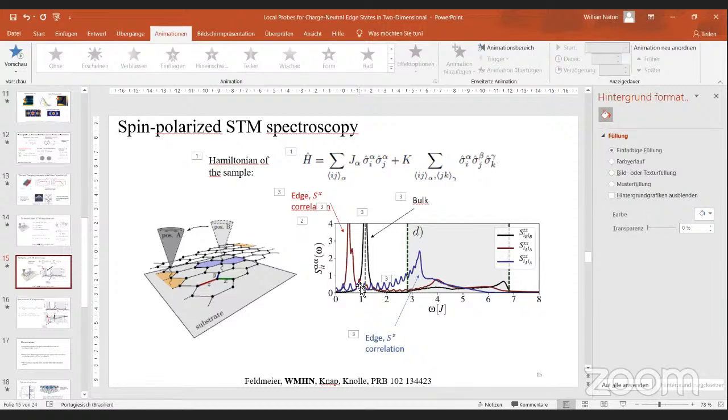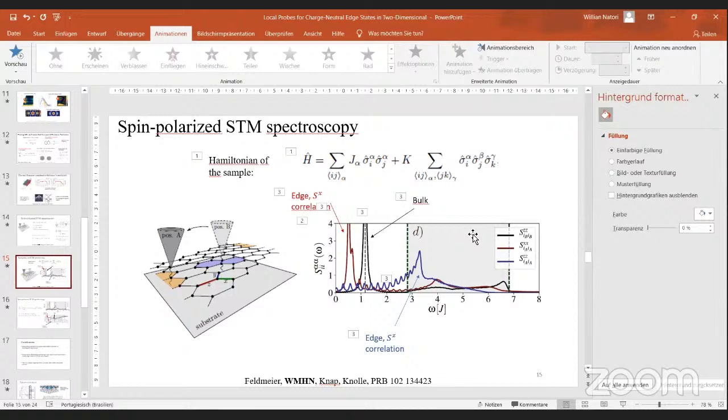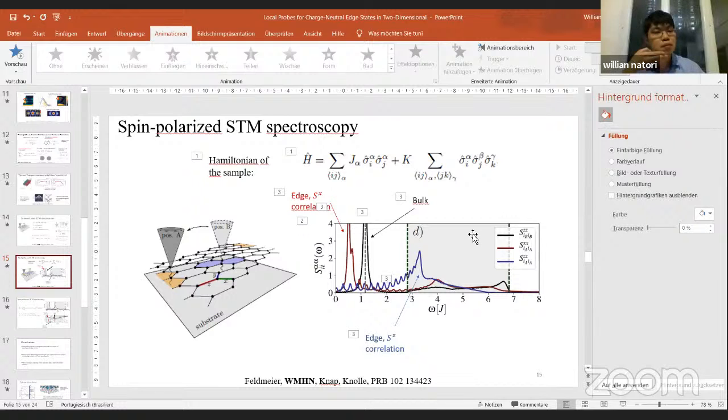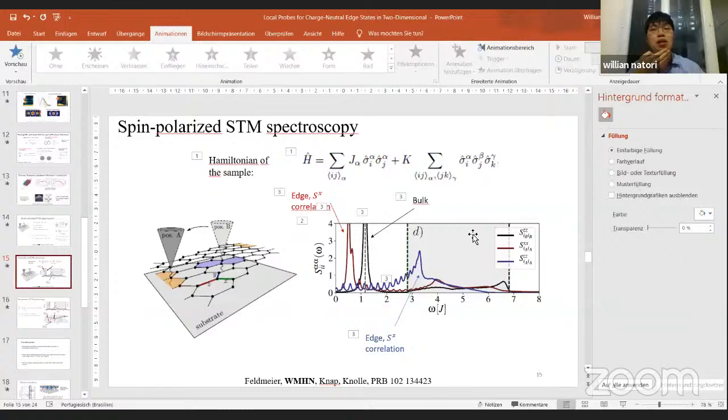For 213, it has this honeycomb structure and the zigzag antiferromagnetic order at 20 Kelvin. So 20 Kelvin is like nothing compared to J. J is like 100 meV, it's like 1,000 Kelvin. So it's a similar kind of thing, these materials always conspire to be semi-classical. But if we apply a magnetic field to sodium iridate, or maybe put it on graphene as a thin film, maybe it'll do the same as ruthenium trichloride. Yeah, maybe. I don't know about it.